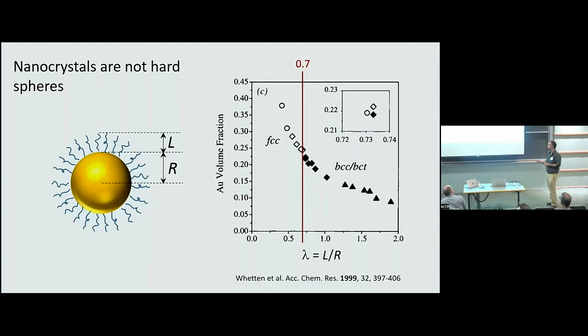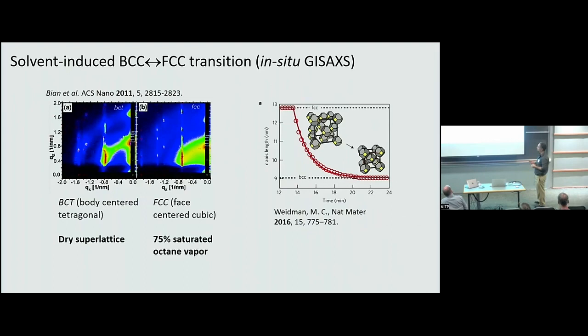Now, there are these two experiments from different papers that actually show that there is another way to trigger the transition between FCC and BCC, and that is by controlling the amount of solvent in the system. So, for example, in this particular one, the dry superlattice has a structure that is BCT, which is a body center tetragonal. I'm going to talk about that in a few minutes, but that's an intermediate in terms of a structure between BCC, body center cubic, and FCC, face center cubic. For now, let's say that this is something that is close to BCC.